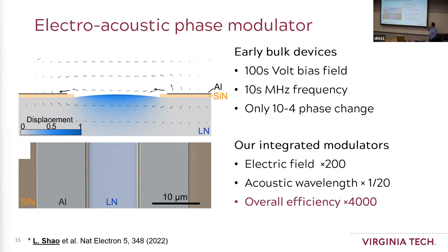But nowadays, we do something different. As I showed before, we make the waveguide and we put the electrodes exactly at the two sides of this acoustic waveguide. In that way, what we improve, first, is that for the same bulk device this gap would be at the millimeter scale, but here it is about 10 micron. So in that way, we can enhance the electric field by over 200 times. What's important is not how much voltage you apply, but the amount of electric field you generate. It is the voltage divided by the distance. So the closer we put the two electrodes, the stronger electric field we can generate. That's the first thing, two orders of magnitude.